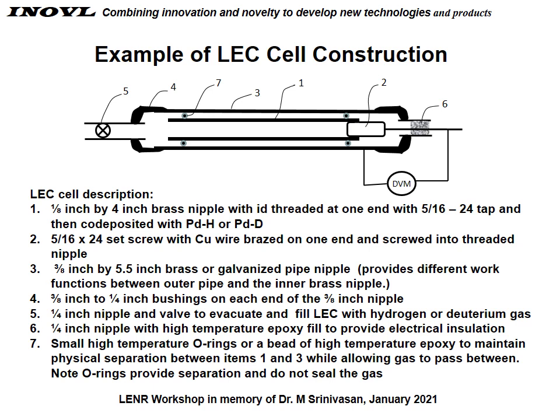The 5/16-24 set screw is screwed into the newly threaded nipple, and this becomes a contact between the working electrode and the outside of the LEC. The 3/8 inch by 5.5 inch brass or galvanized pipe nipple becomes the counter electrode. Bushings at either end of this nipple go from 3/8 inch to 1/4 inch and allow for the connection of a valve at one end to evacuate and fill the LEC with hydrogen or deuterium.